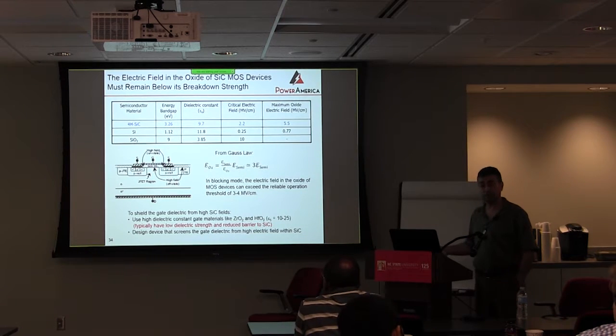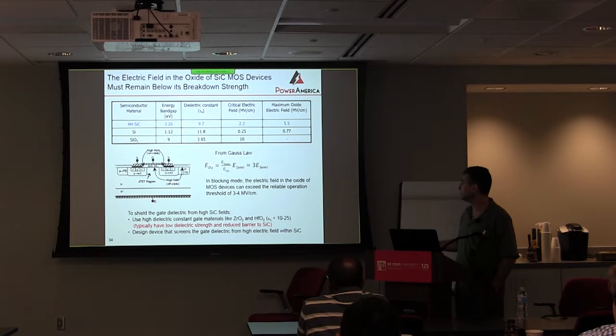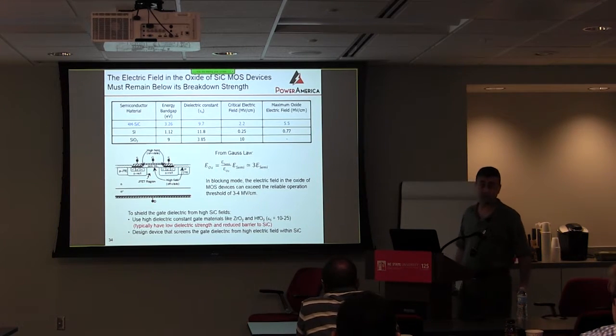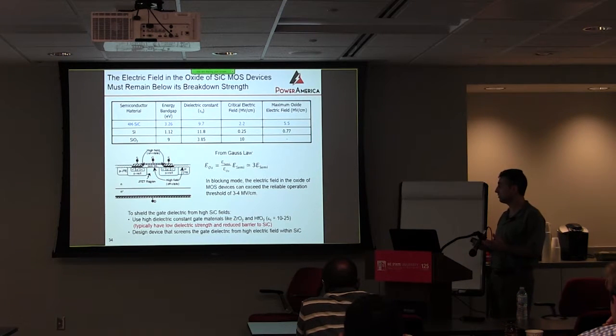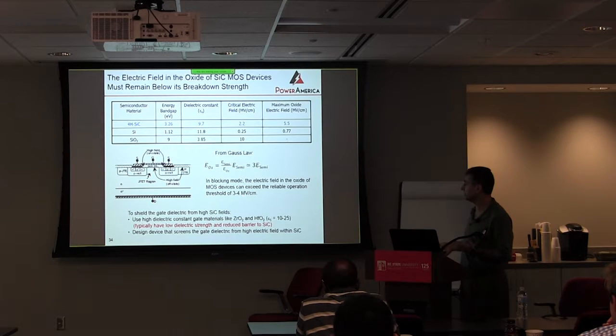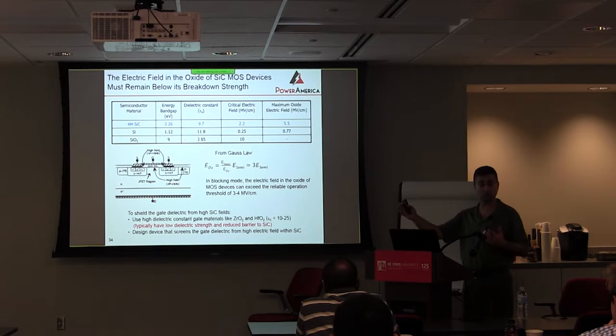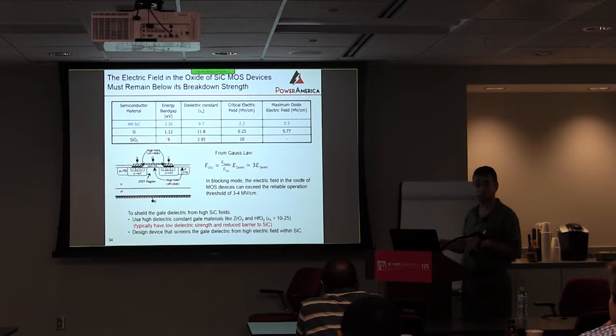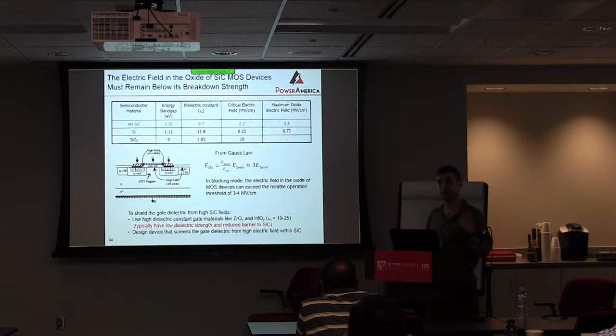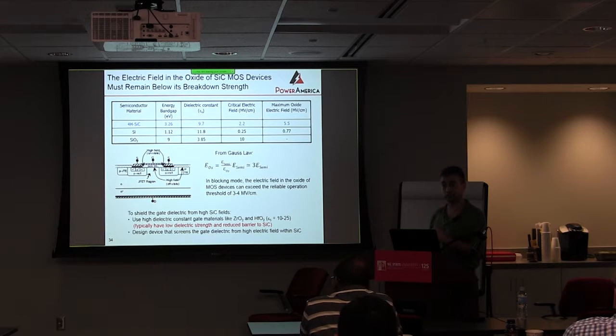And of course, there's an issue in the reverse bias as well. From Gauss's law, the electric field that the oxide sees is the ratio of dielectric constants times the field in the semiconductor. So because of the dielectric constant values that you have here, the oxide sees 3 times the electric field of the semiconductor. So when you're in blocking mode, the field in the oxide can exceed 3 to 4 megavolts per centimeter, and you don't want to go beyond that, because then there are reliability issues with the oxide. Okay, so that kind of sets a limit, and it also creates opportunity for designs where people will use some sort of PN junction structures to protect the gate oxide from seeing that high field. So these are some considerations with respect to the silicon carbide MOSFET, because you're working in that very high voltage regime.